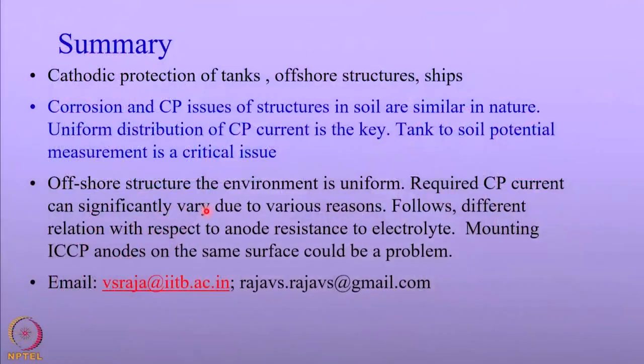Either we use perforated plastic conduits through which the reference electrodes are sent, or it is possible to calculate the potential of the tank at the center if you know the resistivity of the soil, the current density required for cathodic protection, and the measured value of the tank-to-soil potential at the edge.